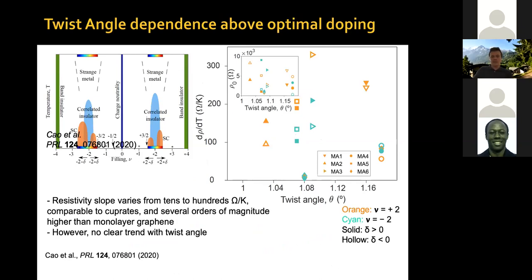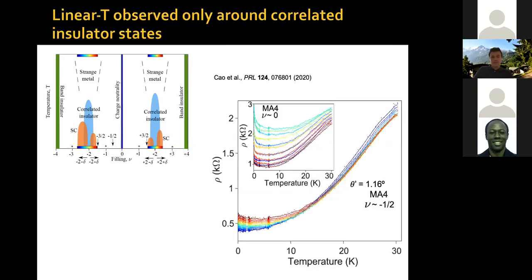The resistivity, though, is very high. The maximum values are of the order of several hundred ohms per Kelvin, which is comparable to the cuprates, or even higher, and several orders of magnitude higher than monolayer graphene, okay? Now, if you go near charge neutrality, so not around the correlated insulator, but near charge neutrality, you see a more standard, more quadratic type of behavior, okay?